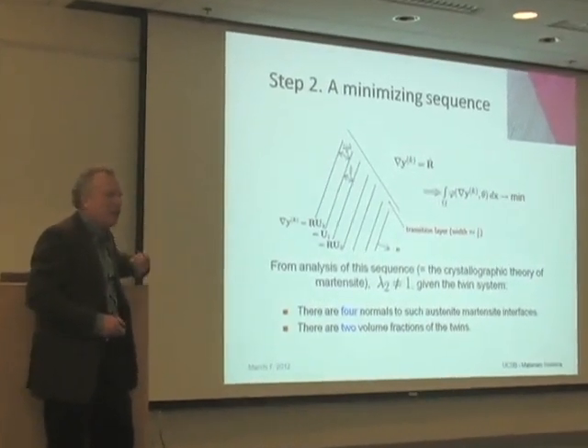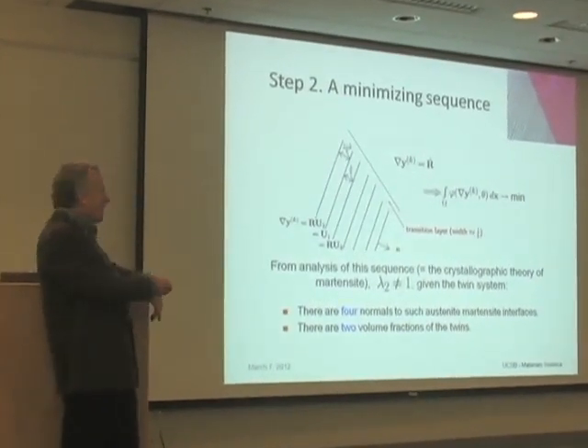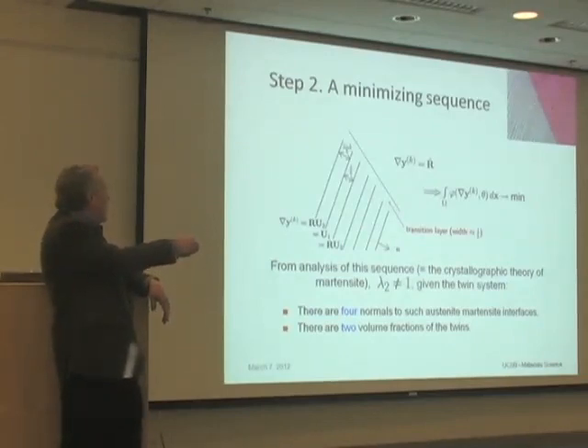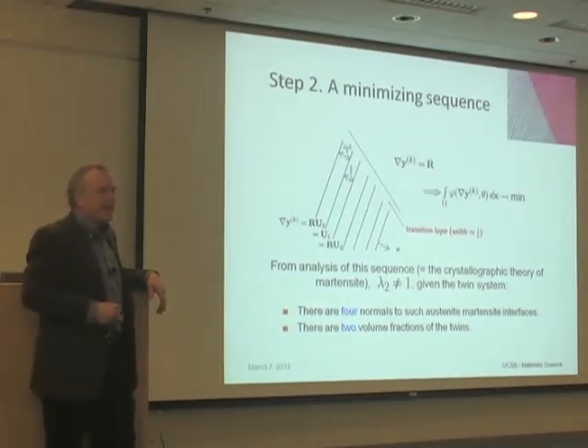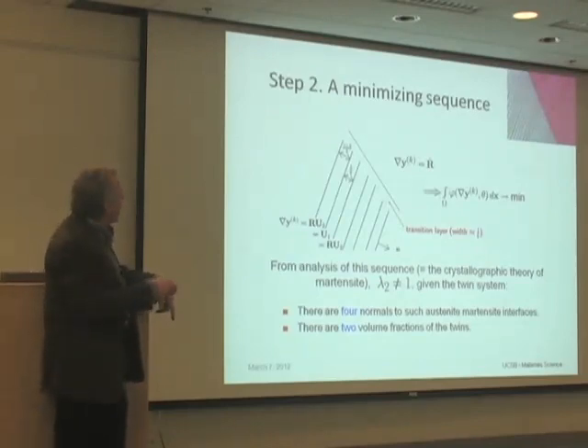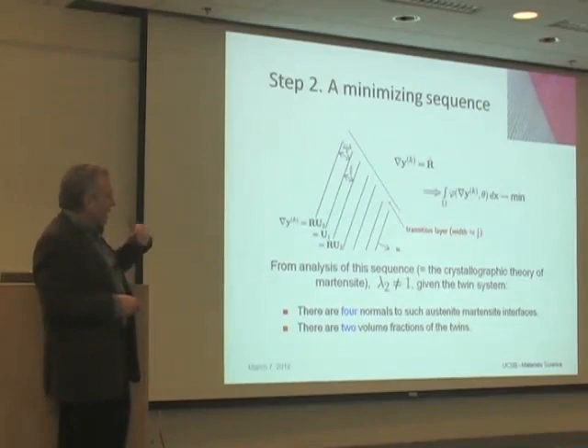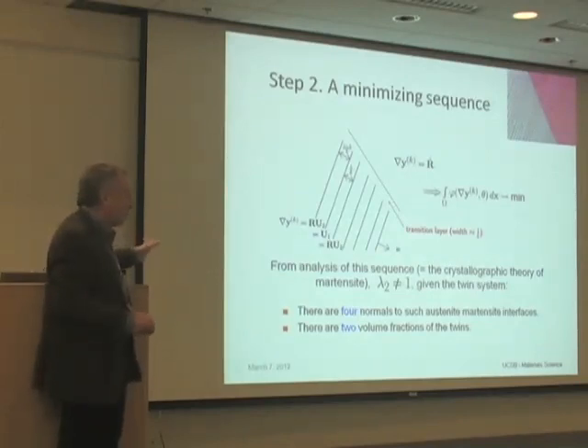It says that the twins need to be infinitely fine, of course, to drive the elastic energy to zero. But of course, the twins over here are not infinitely fine in the picture. And that's also understood. The reason is that there's a small interfacial energy on the boundaries of those bands. By making the twins finer and finer, you drive the interfacial energy to infinity, and so that's unacceptable. If you make them very coarse, the interfacial energy is small, but then the bulk energy of the elastic transition layer is too big.